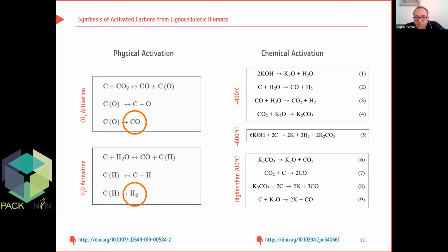So the formed potassium carbonate significantly decomposes into carbon dioxide and potassium oxide at temperatures higher than 700°C, and completely disappears at 800°C. Moreover, the resulting carbon dioxide can be further reduced by carbon to form carbon monoxide at higher temperatures.